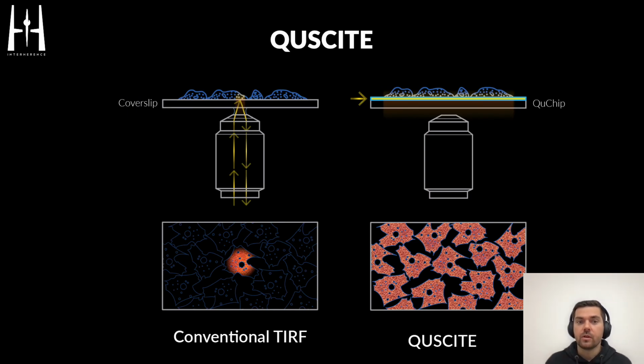We don't do objective-based TIRF. Objective-based TIRF is great, but as said, it has its drawbacks. So what we do is, instead of sending the beam into an objective and then exciting locally a small area of the sample, we exploit a thin film waveguide that is sitting on top of a glass chip that supports a guided mode. And that guided mode has a strong evanescent field tail entering into the sample volume. So when there's now a cell culture sitting on top of the waveguide and there's an optical mode launched into that thin film, the cell culture feels the evanescent field of the waveguide and can start to fluoresce everywhere where the waveguide is. And now you in principle decouple the excitation completely from the detection.